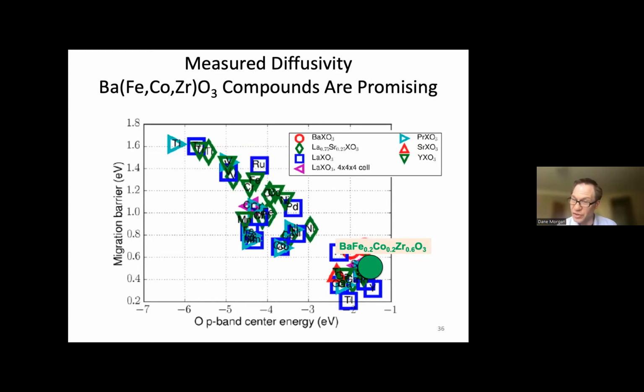In fact, if you measure their diffusion coefficients, they also are excellent diffusers. Their migration barrier for oxygen diffusion is only about half an electron volt. That's in the range of the lowest that have ever been measured in perovskite materials, in fact, in any materials. And you'll see that if you put them on our curve of predictions with this oxygen p-band, we predict they would be right around somewhere in this mess of stuff at around 0.4, 0.5, 0.3, and it comes out at about 0.5. So it came out pretty close to our predictions, certainly well within the uncertainties of our predictive method. So we were very excited about this, both because it's an interesting class of materials and because it really validated that this correlative descriptor approach was yielding qualitative and even semi-quantitative guidance for new materials.